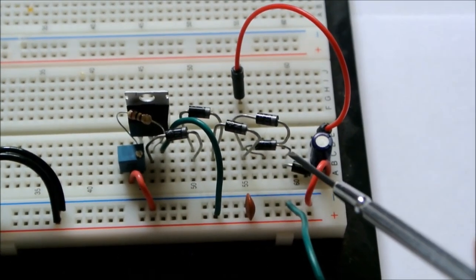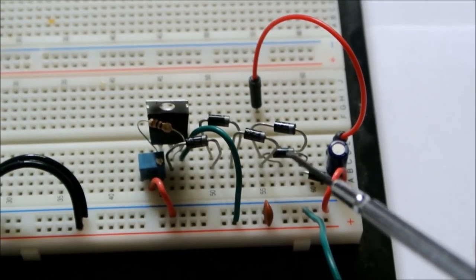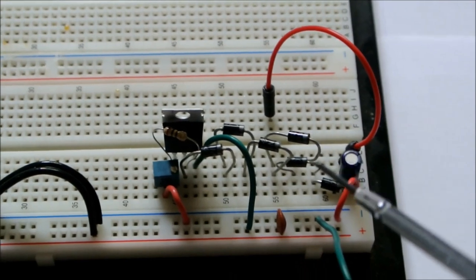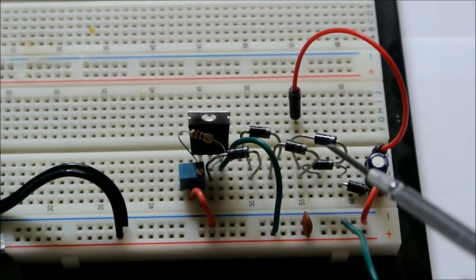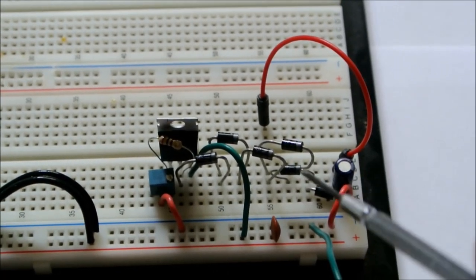And then I have a series of six diodes, and that drops the lowest available voltage from the LM317's 1.25 volts down to about a quarter of a volt. And that lets me get much lower voltages for the crystal growing cell, which translate to lower amperages and better, larger crystals.